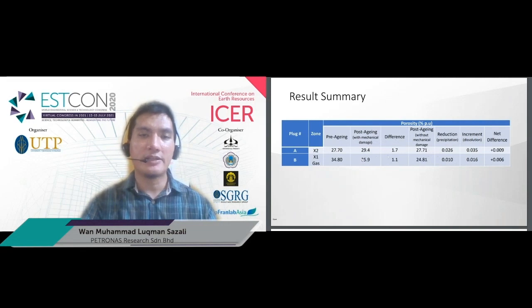If we include mechanical damage, the porosity change is quite high, which is about 1.7 porosity unit percent in plug A of the X2 zone and about 1.1% for the X1 gas zone. However, with the help of DCA and extraction of the middle part without mechanical damage, the actual porosity change due to geochemical reaction is much less, which is about 0.009% in X2 and 0.006% porosity unit in X1 gas.